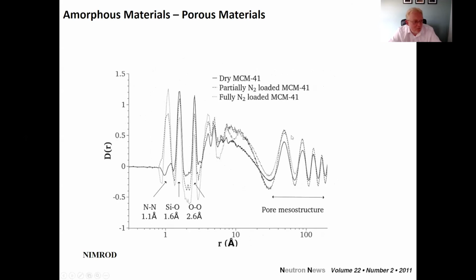And what this gives you, you do a Fourier transform of this information, and you get this pair distribution function information. So you get the nitrogen-nitrogen distance of the nitrogen gas that's physisorbed to the surface of the mesopore. You get the silicon-oxygen distance and the oxygen-oxygen distance. And what you can see is that the nitrogen-nitrogen distance, the intensity of this peak increases as we load with nitrogen, as you would expect.